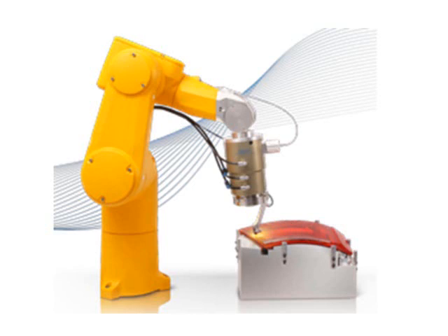Now, if you were to weld this with, say, friction welding, the height changes would create pinch points, and those pinch points would generate more energy at certain spots than others, and you'd have a very inconsistent weld. However, with laser plastic welding, again, due to localized heat, heat's placed only where it's needed, and it's very consistent.